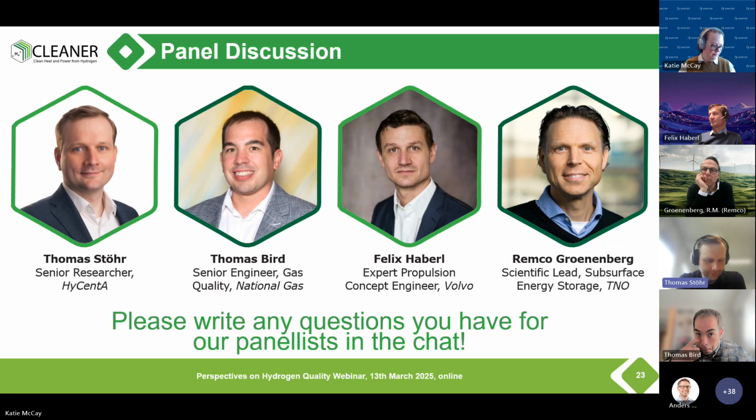Exactly. So I think the first and major issue is the preparation of the pipes itself. In our investigations, we saw that the main source of impurities are the residues that remain within the pipe, and therefore we think that flushing with nitrogen and pigging will be a very crucial part for raising the hydrogen quality, especially at the beginning of the transition process itself.